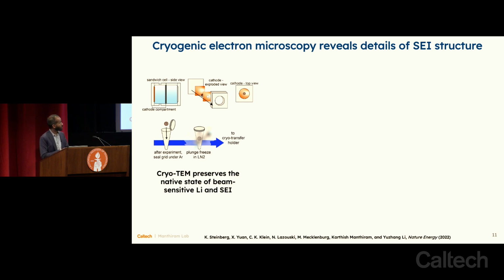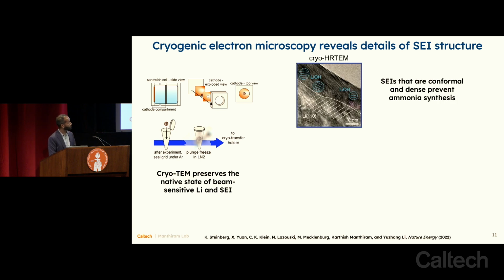And so we developed an electrochemical cell in which we could run this chemistry, that we could then take that electrode, plunge freeze it in liquid nitrogen, and send it into a cryogenic electron microscope. And we can now actually look and see this interface that we have, lithium metal here. We can actually image and see individual atoms. And we can look on the surface here and see a very thin decomposition layer. So this dark region on the surface is the solid electrolyte interface. And it contains domains of, for instance, lithium hydroxide and other more amorphous regions from THF breakdown.